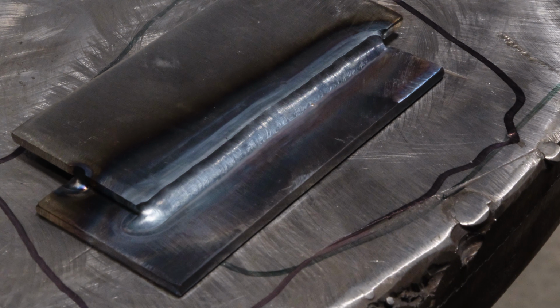Now let's look at a little bit more of a flat angle where we're aiming more towards the root of the joint per se. So as you can see, I have a much flatter tungsten angle. I'm aiming more or less at the root of it rather than that top edge. I'm producing a much smaller fusion weld. Keep in mind, I'm still melting off that plate edge down in order to create filler, but the angle is a lot different, and this is more or less what you would want to do if you're adding filler rather than just trying to melt that whole top edge down. Again, this is just a fusion weld, but everything's looking pretty good, a little bit different of an angle.